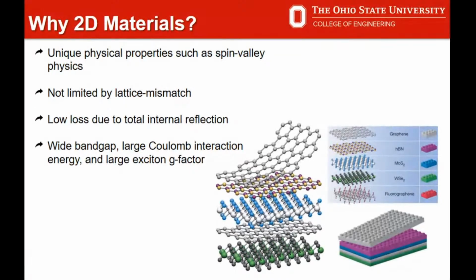So when you're growing some material on top of a substrate, say it is a 3D material, suppose you are growing cubic boron nitride and you are using silicon, the lattice mismatch could go up to 50%. That is huge. That's why people are using diamond substrate, where the lattice mismatch between the substrate and the film is like 1.6 or 5%. So the lower the lattice mismatch between your film and substrate, the better the quality you could expect.